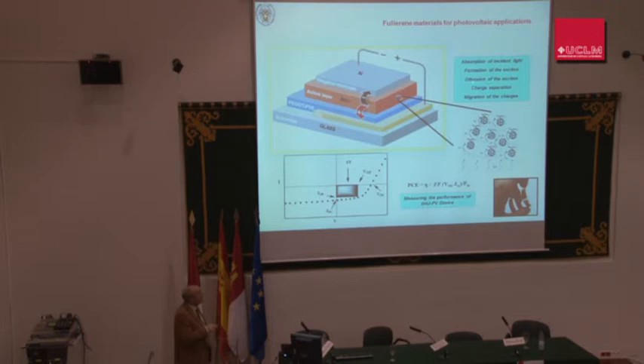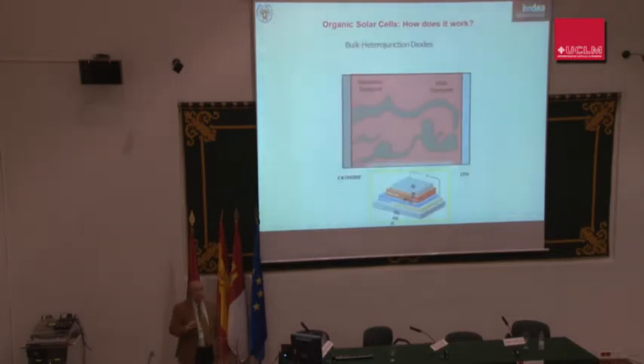So the exciton has to diffuse along the cell, and when the exciton reaches the other phase, that is the situation where a voltage appears, and it is the real situation to produce the charge separation. And once the charges have been separated, migration to the electrodes has to occur later. I will not go into detail about this, as it has already been mentioned, but the efficiency depends on certain photovoltaic parameters like open circuit voltage or short circuit current density.